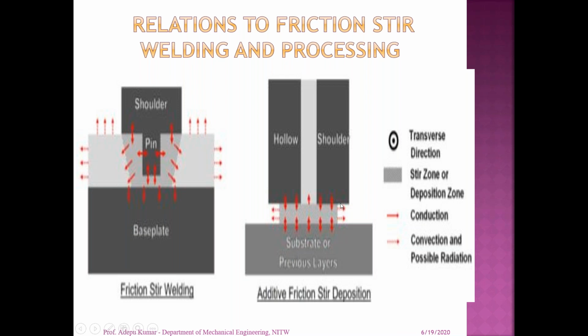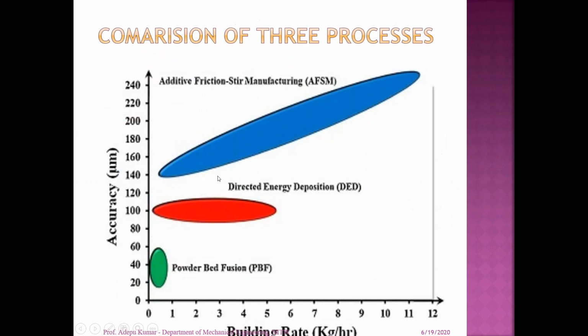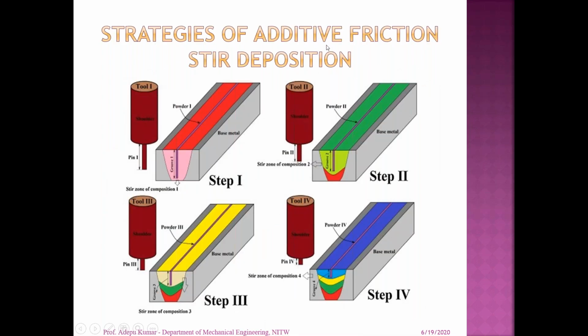You can see the build rate versus accuracy of all three processes: powder bed fusion, direct energy deposition, and additive friction stir manufacturing. You can have more accuracy, and the build rate is also very high compared to direct energy deposition as well as the powder deposition process. So this is the additive friction stir deposition process.